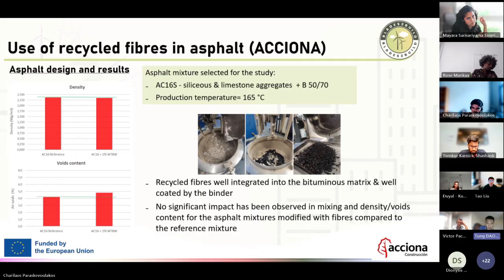They observed that the recycled fibers were very well integrated in the bituminous matrix, that they didn't see any block of the fibers staying locally in one area in the mixture. The fibers were also well coated by the binder, and there's no change or no difference in terms of density or in the void content that I showed to you. So these are good, promising results for the density and void content. Please go to the next slide, please.